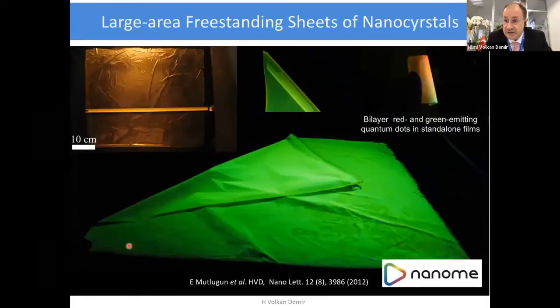This type of quantum emitters are interesting because you can really make them at commercial level. This is one such example that was first shown at the time in a very large area, freestanding sheets. You can think of this as a freestanding or standalone membrane where you can make it several tens of centimeters. Here you see 50 centimeter by 50 centimeter. And you can imagine the challenge here. We have these nanocrystals that you need to make quite uniformly distributed laterally over a meter scale, whereas you'd like to think about the thickness and also vertically have a reasonable distribution.